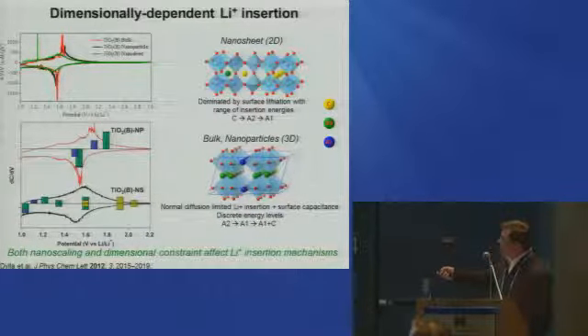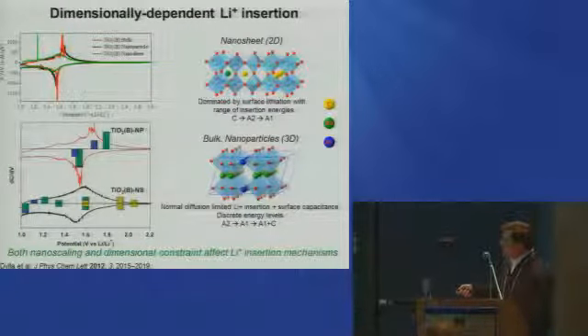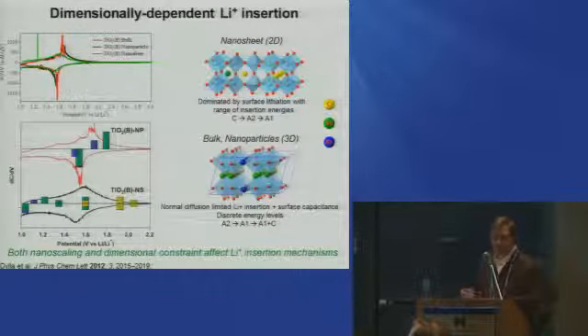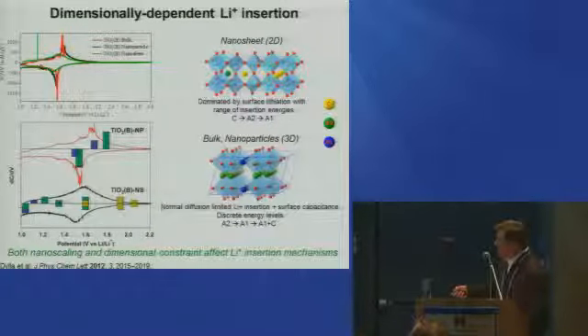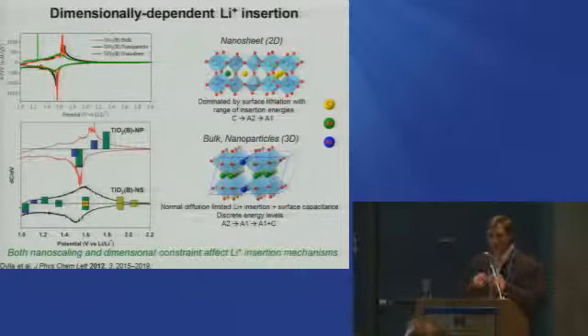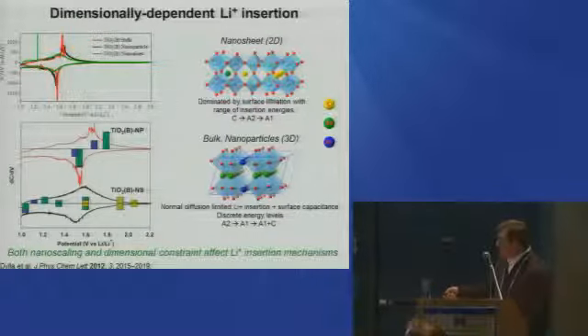And we were able to couple this with high quality DFT calculations performed by Graham Henkelman. And so what we were able to find in this is that if you use nanoparticles, you'll get appearance of two different peaks, basically these two different energetic potentials where lithium sit at certain sites within this TiO2 crystal. There's actually 3 sites that could be lithiated, and in this particular case, it's this A2 site that starts to lithiate first, and then the A1, and then there's a filling of the A and C sites down here. For the nanosheet, because we confined it into 2 dimensions, basically that energy potential dependence spreads out, and the ordering at which sites fill first switches, so we actually can fill the C sites first, then A2, and then A1.